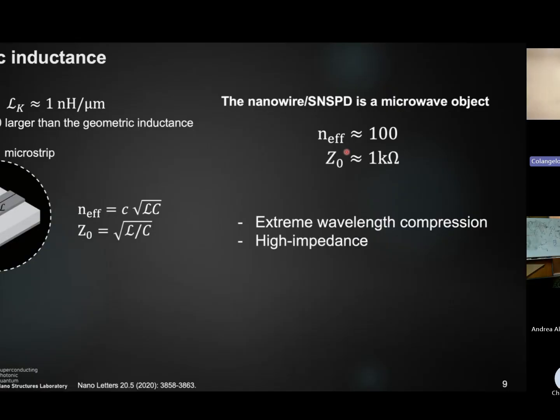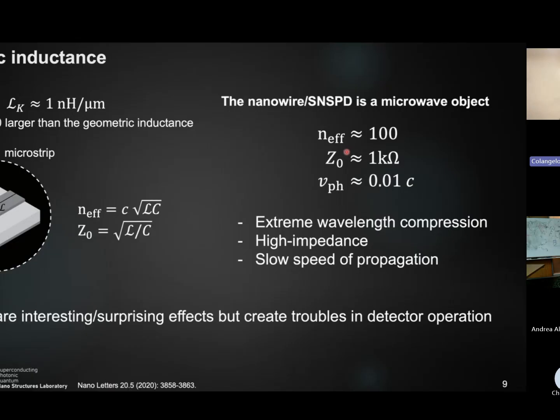The impedance is 1 kilo-ohm, and the speed of light in the structure is 1% of the speed of light in vacuum. So these nanowires do behave as a slow-speed transmission line with a high impedance and extreme wavelength compression. That's very nice because we can actually do fancy things with this nanowire, and this is part of my broader research. However, they are a big problem and a culprit in the trade-offs of the detector, because